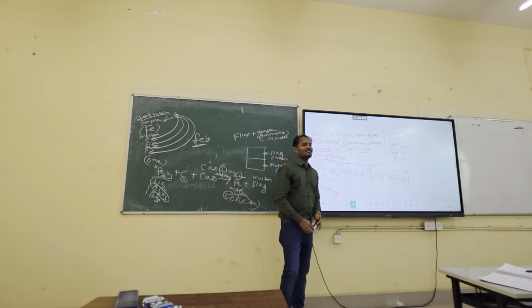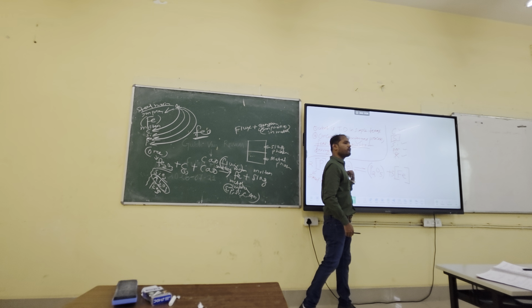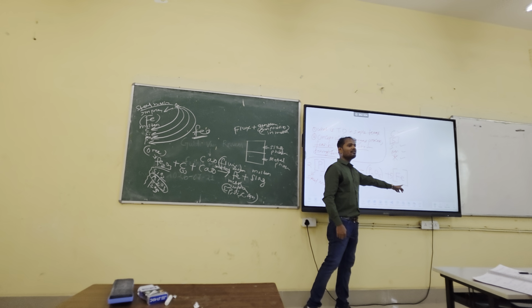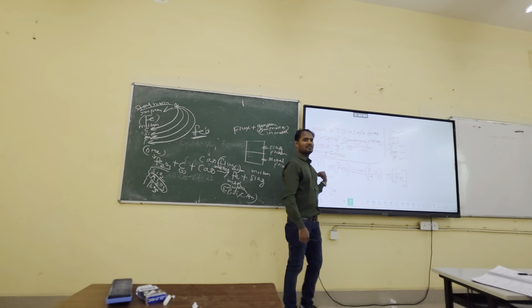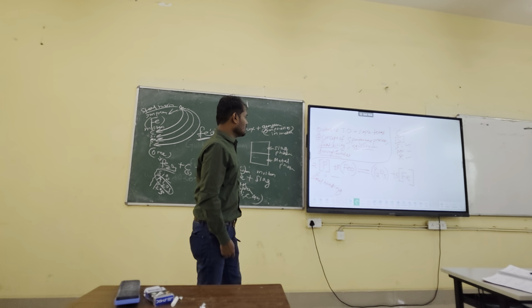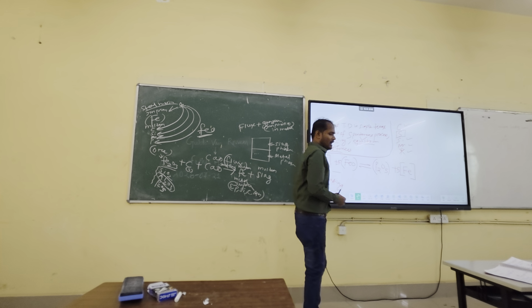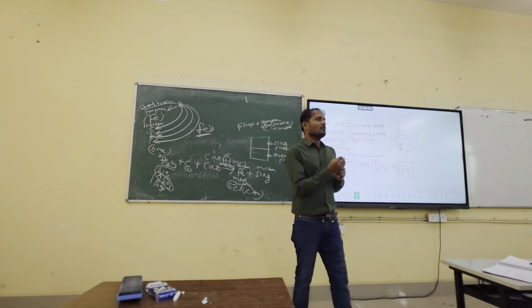Okay. See, this again is very interesting. You have lost some iron in the form of FeO, but you can recover the iron again by this reaction, because this iron will move to where? Metal. Okay, but you have sent the phosphorus to slag by forming P2O5, and this is one of the reactions. Okay, and there is a concept called, you remember, activity.